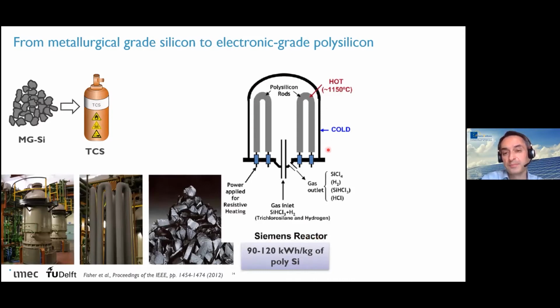So what we do is we use this very pure silicon-containing gas. We have a large reactor at a high temperature of around 1200 degrees, and we actually grow polycrystalline silicon material. So we go from the gas phase to the solid phase, and we end up with a very pure polycrystalline silicon material. Now, one of the downsides of this is that this process requires a lot of electricity, a lot of energy. Typically you need around 100 kilowatt hours to make 1 kilogram of polysilicon.